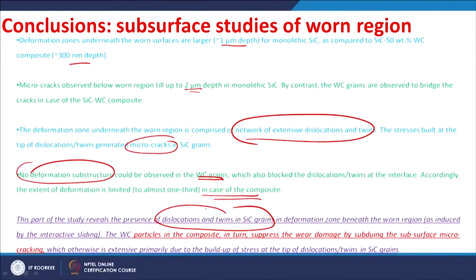So, this particular study reveals the presence of dislocations or twins in the silicon carbide grains in the deformation zone beneath the worn region. The tungsten carbide particles in the composite in turn suppress the wear damage by subduing the subsurface micro cracking, which otherwise is found to be very extensive, mainly because of the build up of stresses at the tips of these dislocations or twins in the silicon carbide grains. So, these stresses were developed because of the interactive sliding. So, the sliding induced stresses are responsible for the cracking. The cracking can be minimized when you use the tungsten carbide particles. That means a composite approach is very much beneficial in suppressing the wear damage by subduing the subsurface micro cracking.